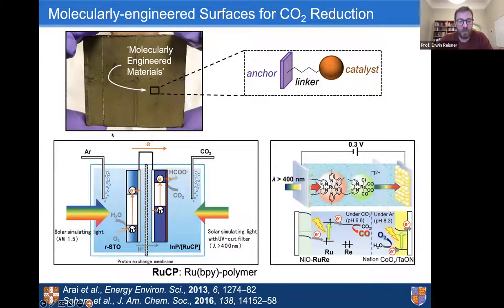In this context, it's also important for me to mention the really important earlier contributions in this field when it comes to CO2 reduction catalysis. On the left, you see a publication by Arai and Morikawa from the Toyota labs in Japan. What they have shown is that you can build a photoelectrochemical cell. On the cathodic side, for CO2 reduction, they're using an indium phosphide semiconductor that's coated with a ruthenium polymer, and this ruthenium polymer can reduce CO2 to formic acid. On the right-hand side is another example, also from Japan, where Ishitani, Abe, and Maeda were involved. They're also modifying semiconducting surfaces, in this case a nickel oxide photocathode with a dye, a ruthenium light absorber, and then a rhenium CO2 reduction catalyst. This one would reduce CO2 to carbon monoxide.